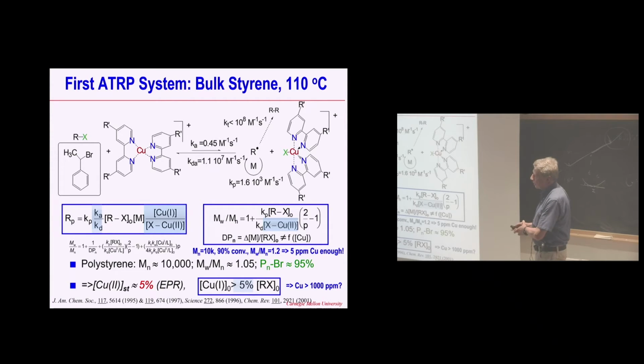So this typically happens, it's an example from bulk polymerization of styrene, so no solvent, 110 degrees, above glass transition temperature. And if you look at the rate of polymerization, it shows you this ratio of activation, deactivation rate constants, and also a ratio of copper 1 to copper 2. So formally, rate of polymerization should not depend on a concentration of copper, but only on a ratio of copper 1 to copper 2. So if you can keep the ratio the same, you can reduce the amount of copper 10 times, 100 times, 1,000 times, a million times. You should have the same rate of polymerization.